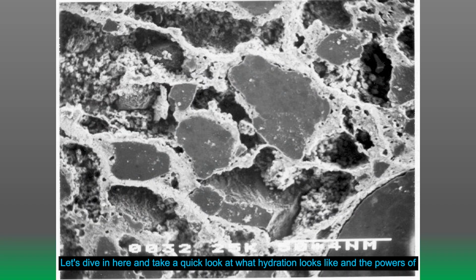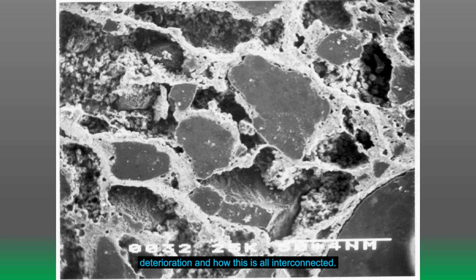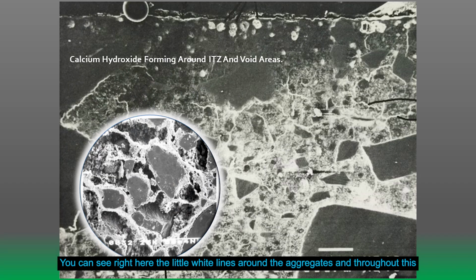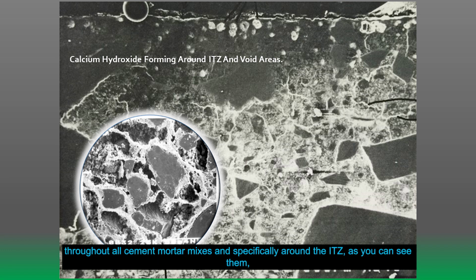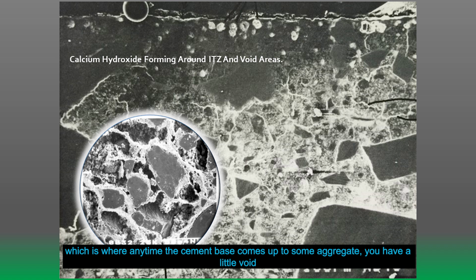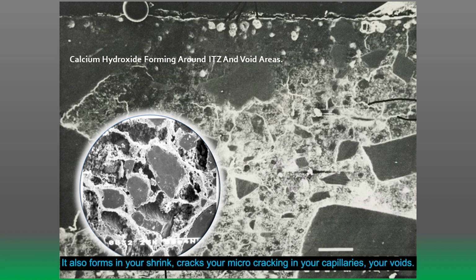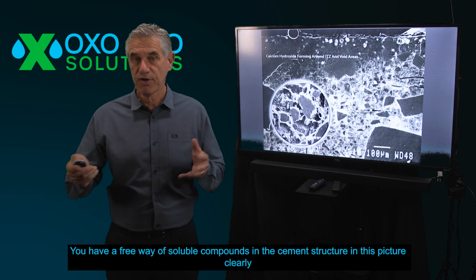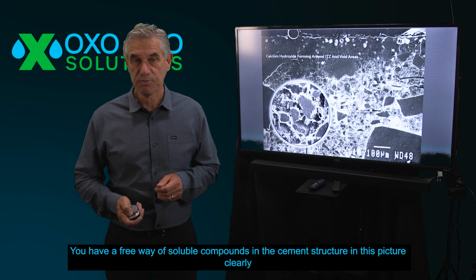And here's what we intend to do with that. Let's dive in here and take a quick look at what hydration looks like and the paths of deterioration and how this is all interconnected. You can see right here the little white lines around the aggregates, and throughout this matrix is the calcium hydroxide forming, and it forms like a freeway or a spider web throughout all cement mortar mixes. And specifically around the ITZs, anytime the cement paste comes up to some aggregate, you have a little void space that's created by the water separating, and the calcium hydroxide forms in there. It also forms in your shrink cracks, your micro cracking, your capillaries, your voids. And you remember, this is a 3 on the Mohs hardness scale. It's very soft, it's very soluble. You have a freeway of soluble compounds in the cement structure, and this picture clearly shows that.